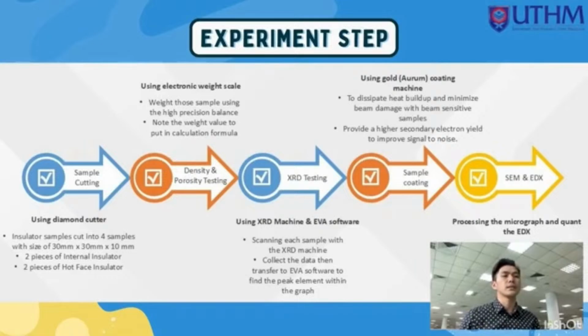And then we can do the density and porosity testing using an electronic weight scale. Weigh those samples using a high precision balance and note the weight values to put in the calculation formula. And then we do the XRD testing using an XRD machine and EVA software, scanning each sample with the XRD machine and then collecting data to transfer to EVA software to find the peak elements within the graph.